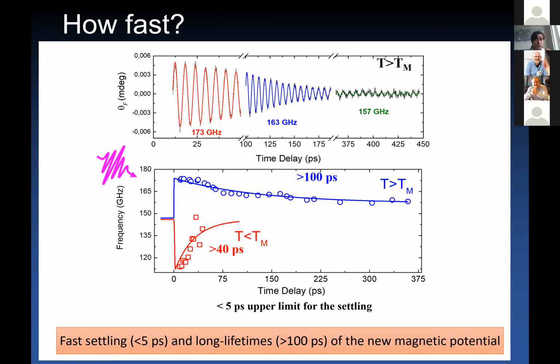Yeah, good question. As far as I know, there is no structural change associated with this transition, but there's an activation of the Dzyaloshinskii-Moriya interaction. Along with the reorientation of your spins, you activate a Dzyaloshinskii-Moriya interaction, which causes the canting of your spins. Associated with this transition, there's also a change in the orbital occupation, in the thermal occupation of the dysprosium manifold. You have these 4f electrons in the dysprosium that are changed in the multiplet as a function of temperature. That is believed to be the cause of the transition.